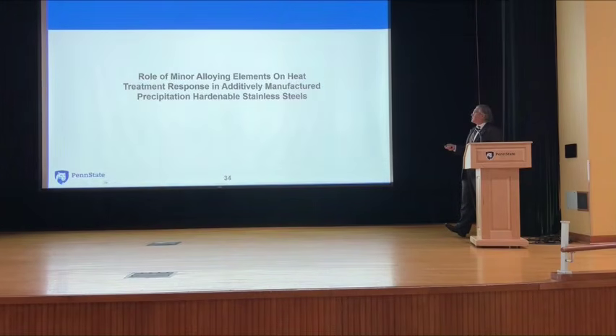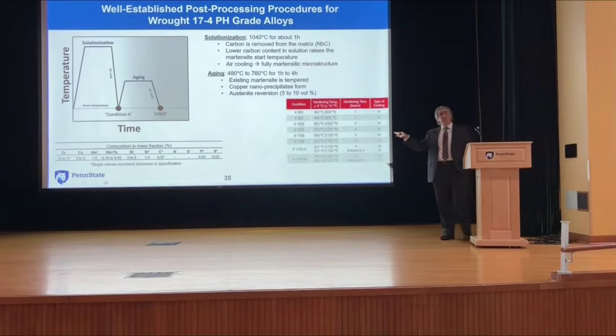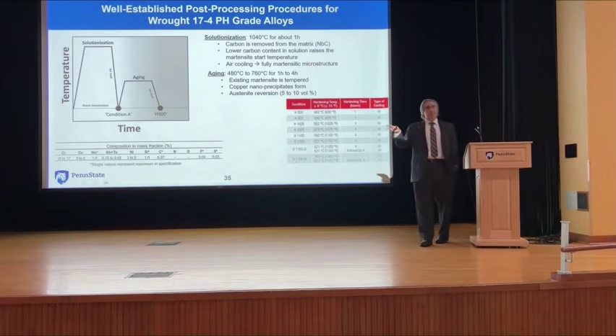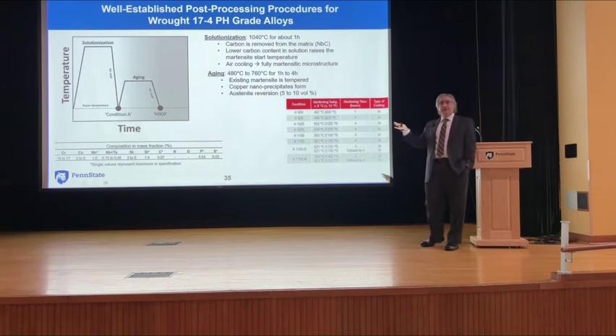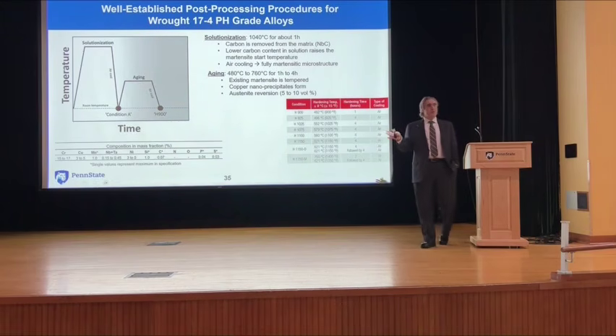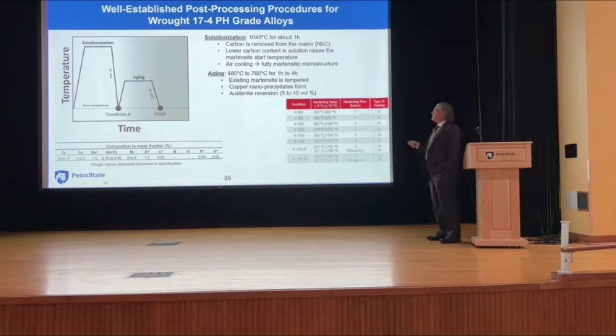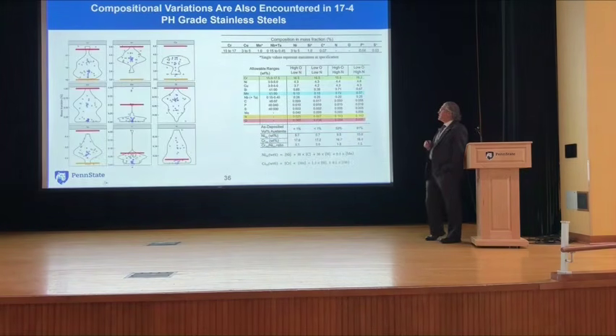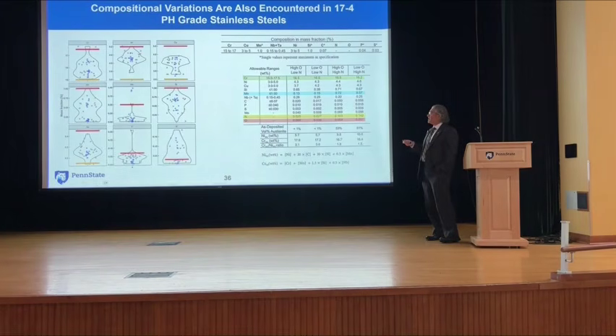Now, the role of minor alloying elements, how do they impact it? So I'm going to jump to 17-4 as a precipitation hardened stainless steel. You'd say, what's that? This is used constantly. About every turbo machinery component you can think of has 17-4 somewhere in it. And the precipitation hardening means it needs to be heat treated. We do a couple different heat treats to it, but once again, this was the same type of idea: how much do things vary?